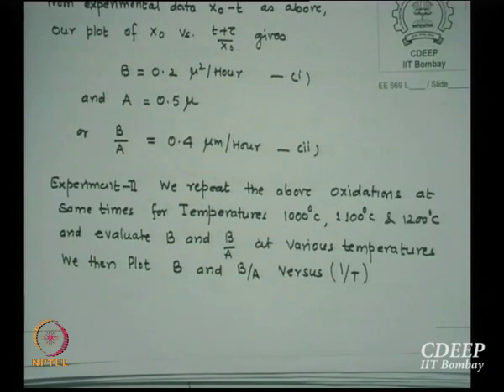Now I'll repeat this experiment at different temperatures, again measuring oxide thicknesses. The only thing is now I may do it for a given time, I mean the same time. Even if you do different times, the graph will show the slope, so it doesn't really matter, but preferably you do the same so that you know where the slopes are moving, just to see them.